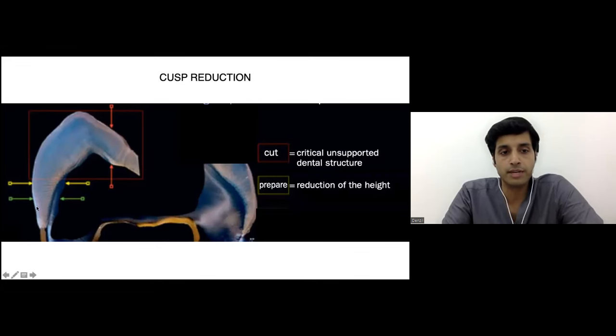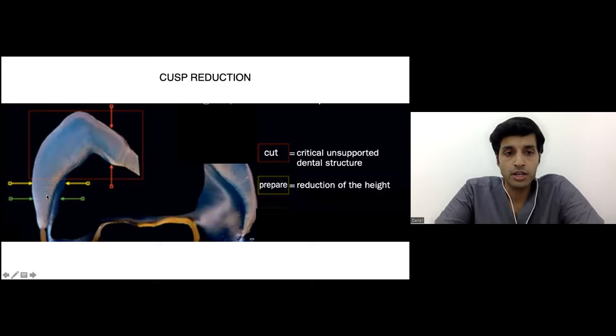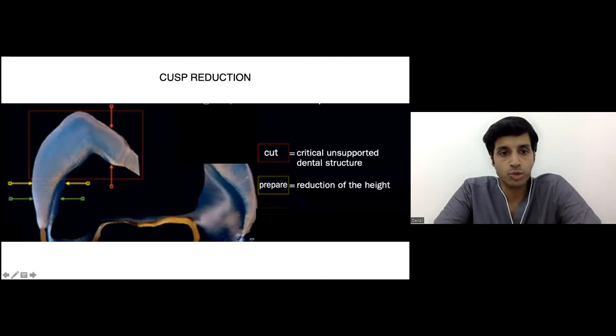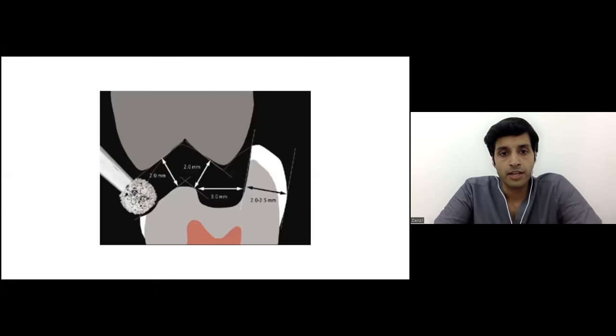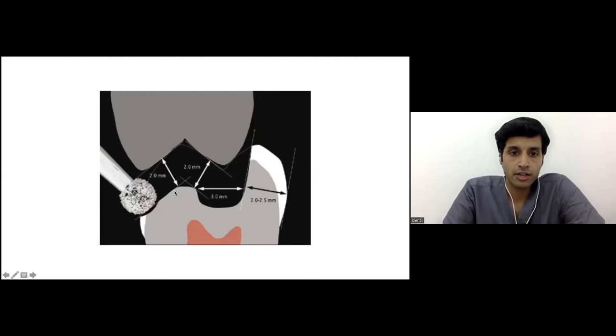As much of this part will be preserved, that will be good, because at the stress concentration areas we want enamel to be there, because the bonding of enamel to this area will be the highest and most predictable in the long term. That is, the green arrows will be hybridization and use of flowable or fiber reinforced composite. So the cusp reduction, as for any indirect process, needs to be uniform. It needs to be at least 2 millimeters